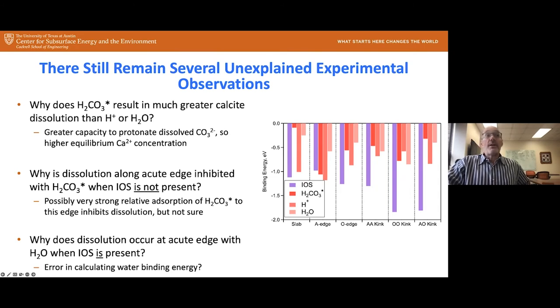Another thing we have a harder time explaining is why dissolution along the acute edge is inhibited with carbonic acid when IOS is not present. That's something we haven't figured out. One possibility is that carbonic acid binds so strongly to that edge site that it's kinetically limited and it takes time. The last thing we can't really explain is why dissolution occurs at the acute edge with the water when IOS is present. Remember, IOS has a more favorable binding energy than the water, so you'd think you'd also arrest it on the acute edge for the water case, but we don't. I'm not sure if we need to think about how we calculate that binding energy for the water in this system, but that's something we're still thinking about.